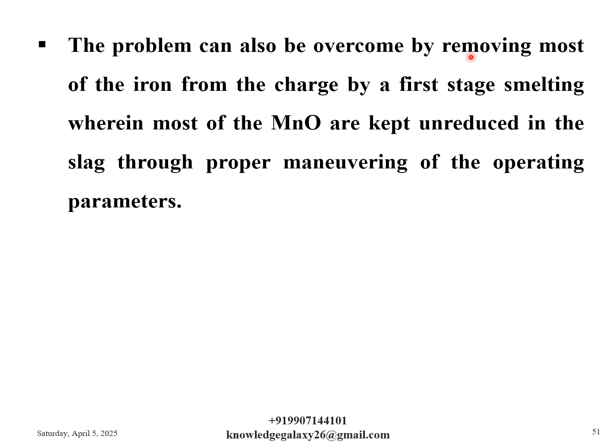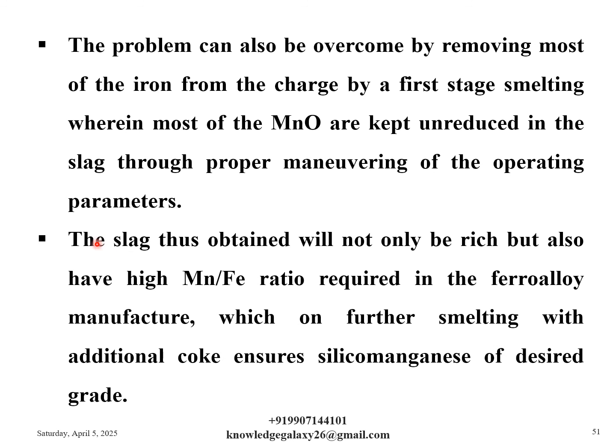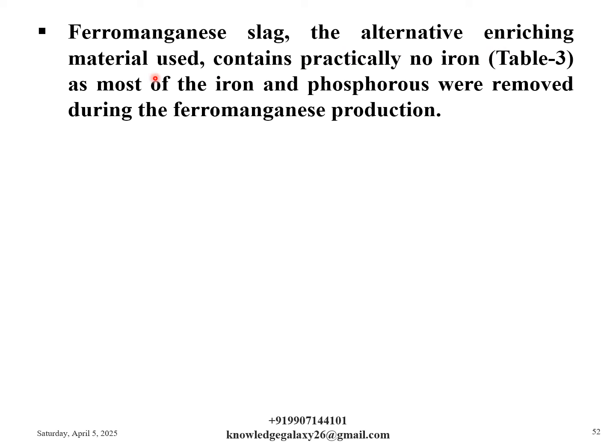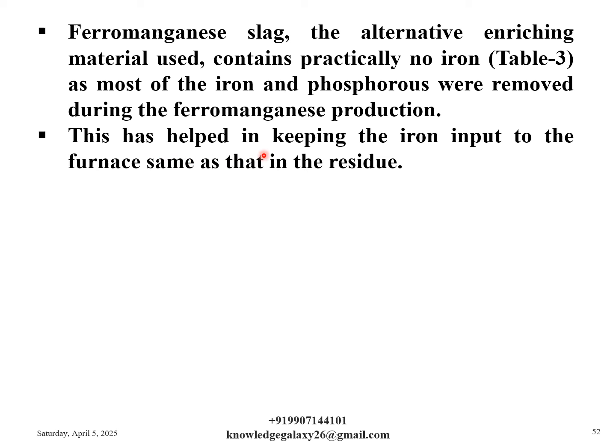The problem can also be overcome by removing most of the iron from the charge by a first stage smelting, wherein most of the MnO is kept unreduced in the slag through proper maneuvering of the operating parameters. The slag thus obtained will not only be rich but also have the high Mn by Fe ratio required in ferroalloy manufacture, which on further smelting with additional coke ensures silicomanganese of desired grade. Ferromanganese slag, the alternative enriching material used, contains practically no iron, as depicted in table 3 analysis, as most of the iron and phosphorus were removed during the ferromanganese production. This has helped in keeping the iron input to the furnace the same as that in the residue.